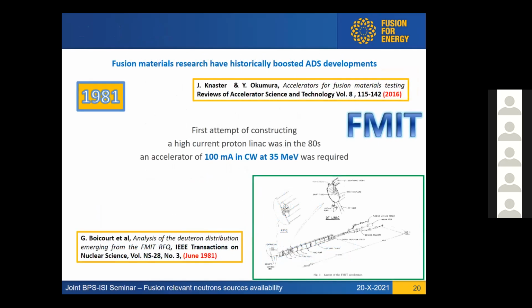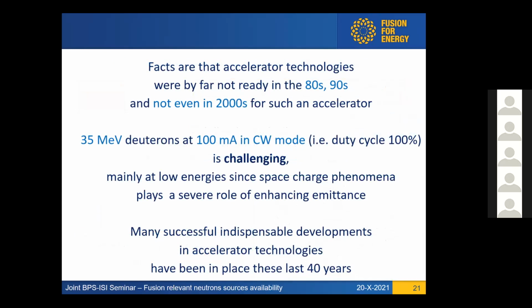So in the 80s, as I was mentioning before, the US started in a very aggressive manner the development of an accelerator. They were expecting to have 100 milliamps in continuous wave at 35 mega electron volts. These were the conditions of the project at the time, so they would be getting slightly lower yield of neutrons, that's clear. The project was called FMIT, Fusion Materials Irradiation Test Facility. And here you have the schema of the accelerator. They started very strongly, but they faced difficulties. The reality is that at the time, the technology was not ready.